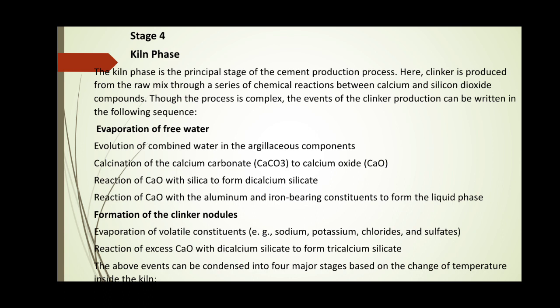Evaporation of free water. Evolution of combined water in the argillaceous compounds. Calcination of calcium carbonate, that is CaCO3, to calcium oxide, that is CaO. Reaction of calcium oxide with silica to form dicalcium silicate. Next, reaction of calcium oxide with the aluminum and iron bearing constituents to form the liquid phase. Formation of the clinker nodules.